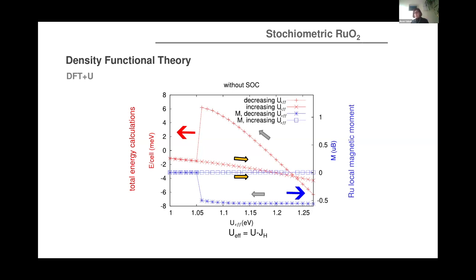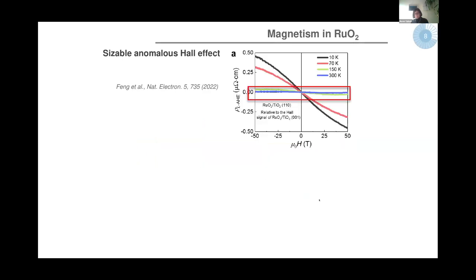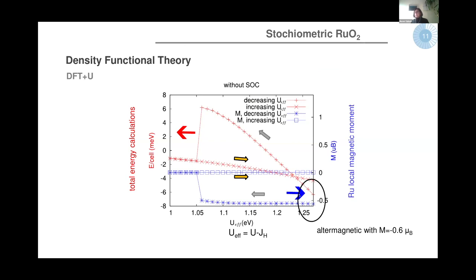Now, the other type of calculation is to start at very large U, so to really bias the system into a magnetic solution, which would be now here, these values of U, where in fact the magnetic moment that the ruthenium acquires is very large, it's minus 0.5, much larger than what the experiments that claim to see altermagnetism seem to observe. And as you can observe, the energy at these very large U values of this magnetic solution is indeed the lowest one. So you would say in this region, I'm going the other way around, we indeed find an altermagnetic ordering.